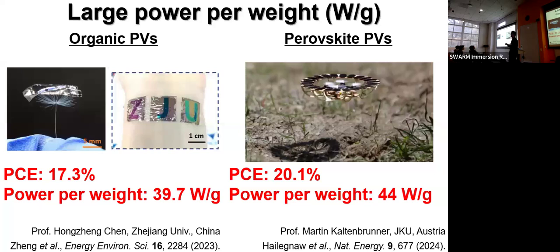The left shows the organic PV cases reported by Professor Hongzheng Chen, Zhejiang University, China. In their studies, they achieved a power conversion efficiency of 17.3%. Then they reached a power per weight value of 39.7, almost 40 watts per gram. For perovskite cases, Martin Kaltenbrunner from JKU, Austria, achieved a PCE of 20.1%, and a power per weight value of 44 watts per gram. And then they put such a very thin perovskite solar cell onto drone surfaces to make the power supply system for the drone system.